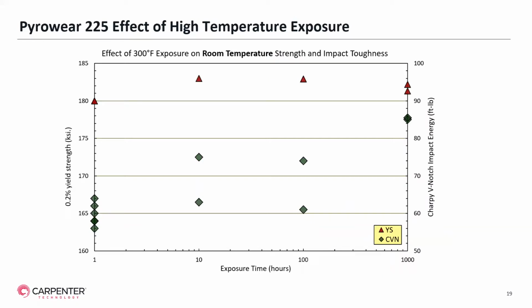We've looked at the effect of long-term exposure at modest temperatures, in this case 300 degrees Fahrenheit, where we've exposed the quenched and tempered Pyrowear 225 to times up to 1,000 hours at 300 degrees Fahrenheit, and then pulled tensiles and broke Charpys at room temperature to see what the effect of that long-term exposure was. As you can see, the red triangles, again, illustrating yield strength. Along the x-axis are the log of exposure time from 1 hour up to 1,000 hours. And as you can see, the yield strength is unaffected by this long-term exposure at 300 degrees Fahrenheit, where we're still getting at least 180 KSI yield strength.